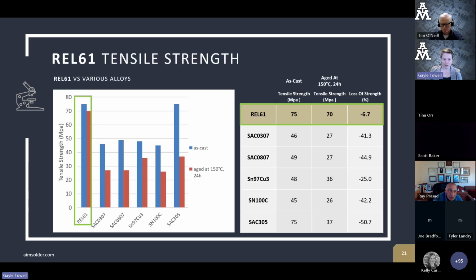This is my favorite one. This is the tensile strength as cast and after aging. And there's such a stark difference here between REL61, SAC305, and many of these other SAC alloys and SN100C. We first cast all of these different alloys and measure the tensile strength. And we see REL61 as being one of the winners. SAC305 gives the same tensile strength. They look equally strong when you first cast them.